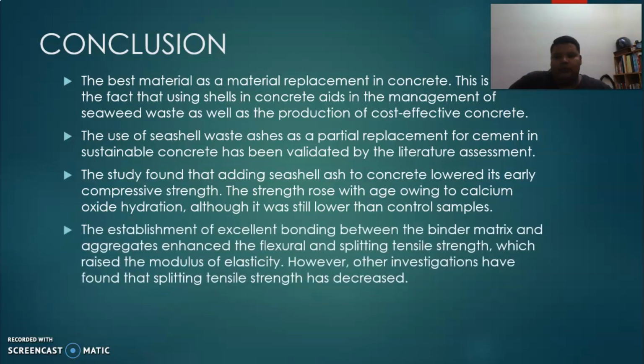The establishment of excellent bonding between the binder matrix and aggregates enhanced the flexural and splitting tensile strength, which raised the modulus of elasticity. However, other investigations have found that splitting tensile strength has decreased.